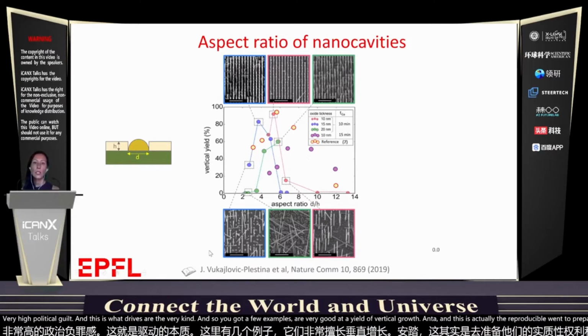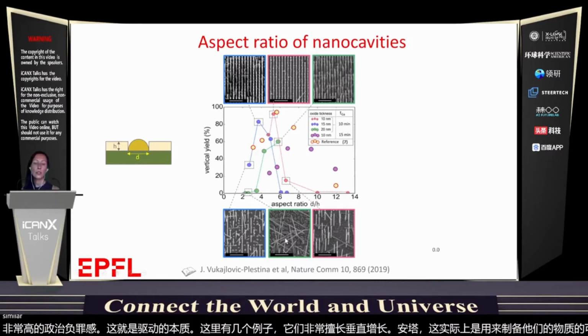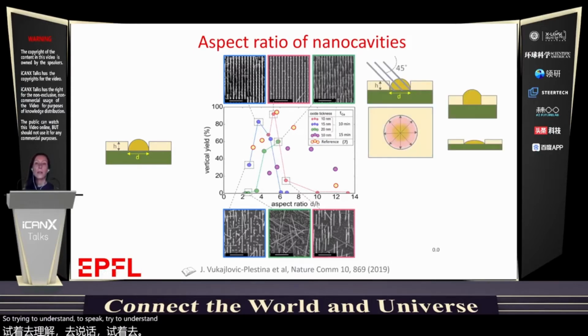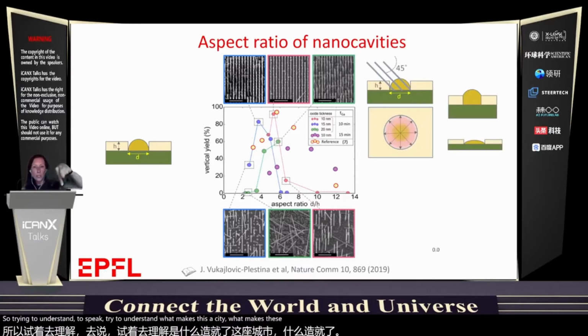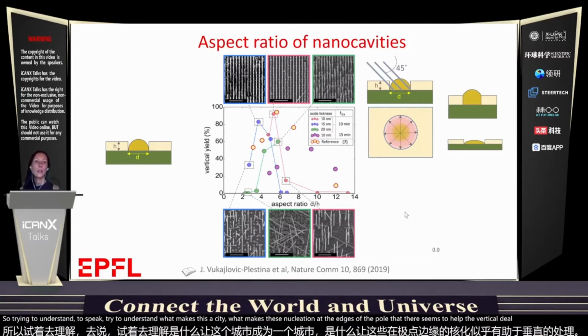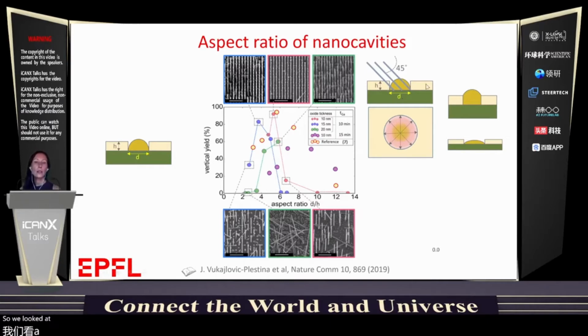And if you don't do this, you see how similar growth conditions, or in fact, the same growth conditions lead to a full disaster. So trying to understand this, we tried to understand what makes this asymmetry, what makes this nucleation at the edges of the hole that seems to help the vertical yield. So we looked at the cross-section here.